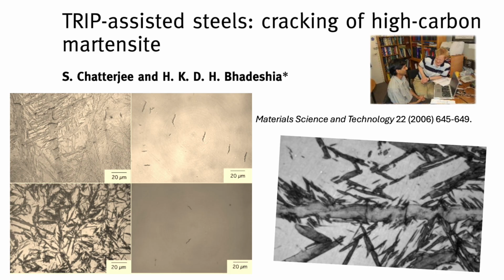Oh yeah, what do they do? They took a steel designed to mimic the high carbon content you'd find in that retained austenite in TRIP steels. Then they heat treated it at different temperatures before quenching. Why different temperatures? Because the austenitizing temperature directly controls the austenite grain size. Higher temperature, longer time means bigger grains. So they could create samples with a whole range of grain sizes.